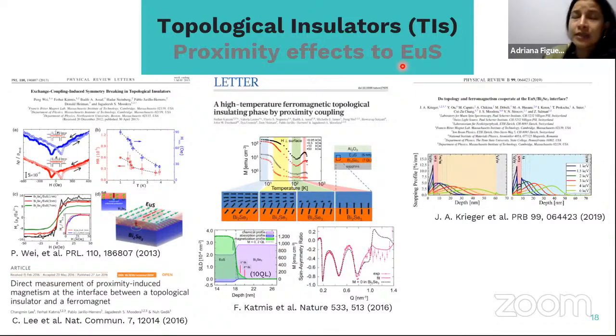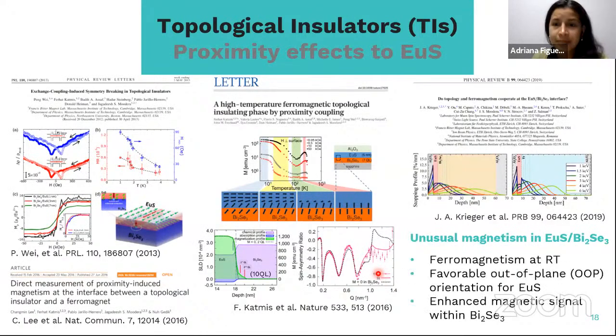The first material that was used and has been studied very widely is europium sulfide. Then there have been several reports about the properties, not only transport properties, but also properties of these interfaces of the topological insulators with europium sulfide. And they have observed very interesting phenomena. In particular, they have observed unusual magnetism in these interfaces.